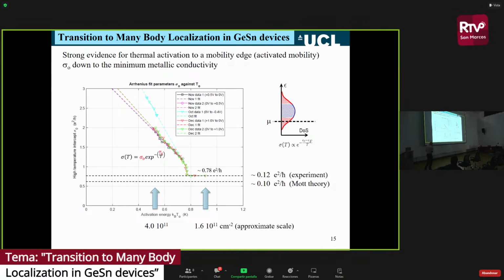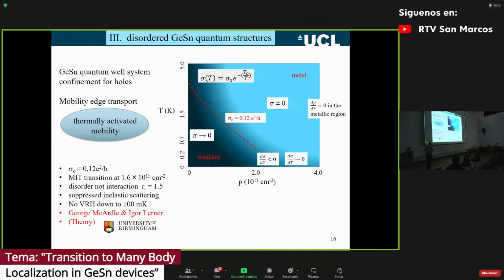There are several things that could be happening here. We think there's possibly a gap in the density of states. If there's a gap in the density of states, it looks like an Efros-Shklovskii hopping mechanism, because the introduction of this excitonic state gives you a band gap that is linear in energy. But what we don't get is the temperature dependence of the conductivity that would indicate hopping.